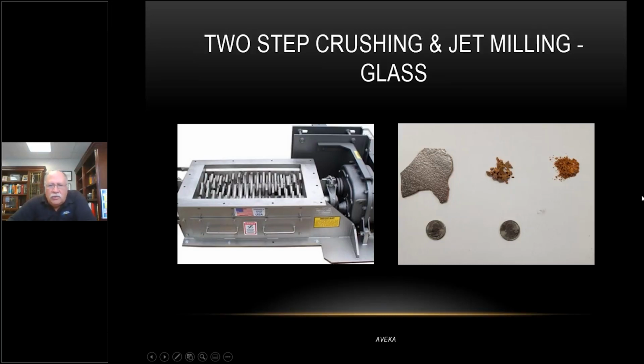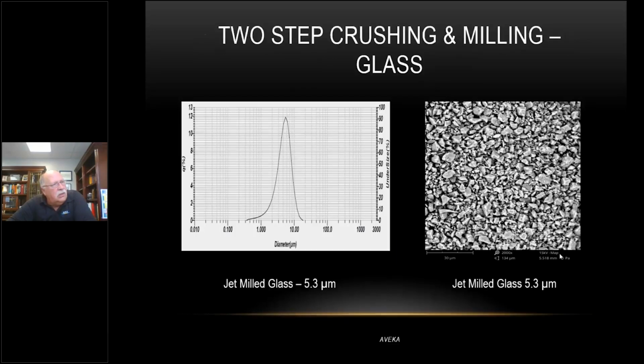What happens is by doing this, instead of it taking hours and days and years to grind up material, we can do this in a very fast and facile fashion. So this is the results that we get. We were taking these big pieces of glass, grinding them down to a nice tight distribution, around 5.3 microns, and here's the SEM picture that we actually get in a situation like this.